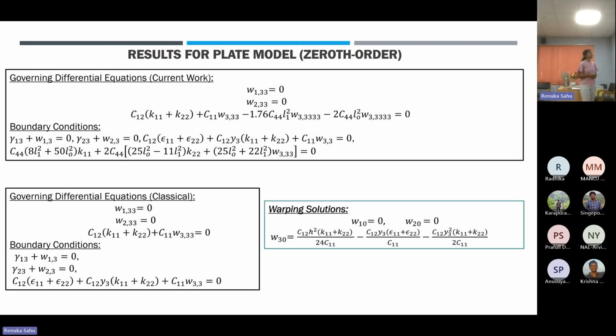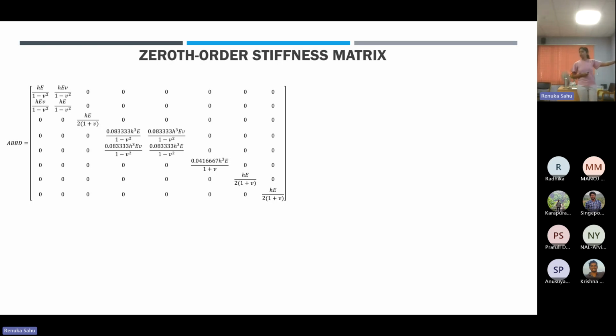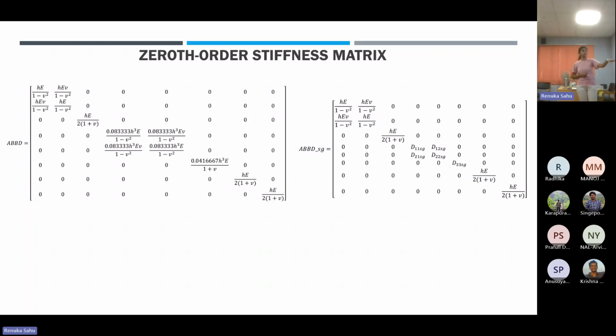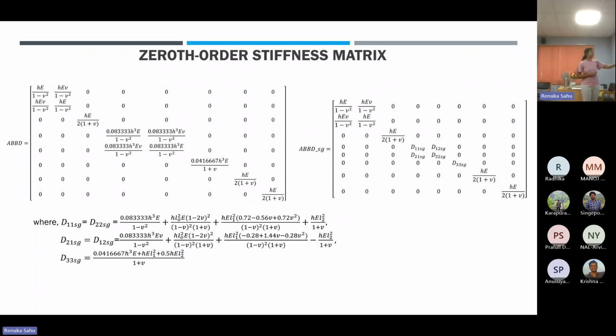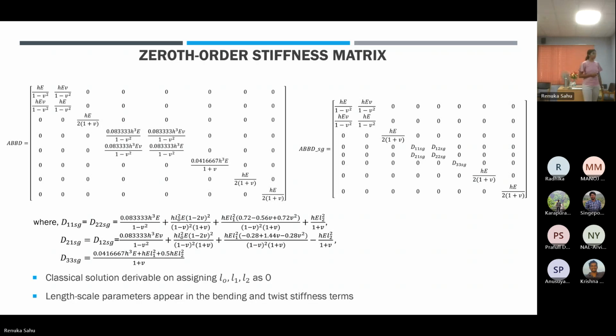So we get the following governing differential equations and boundary conditions, and these are the 0th order warping solutions. This is the classical 0th order stiffness matrix, and here we have the strain gradient 0th order stiffness matrix. We can see material length scale parameters appearing again in the bending stiffness systems and the twist stiffness systems. We can derive the classical solutions once we assign L0, L1, L2 as 0, and the length scale parameters appear in the bending and twist stiffness terms.